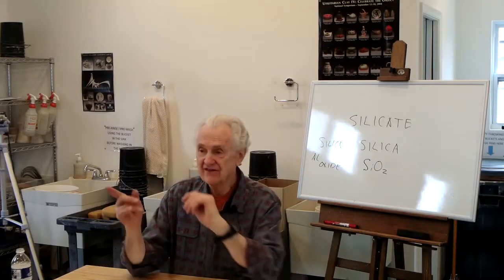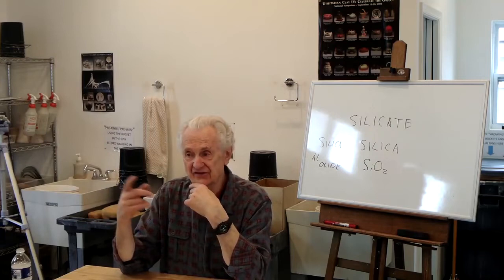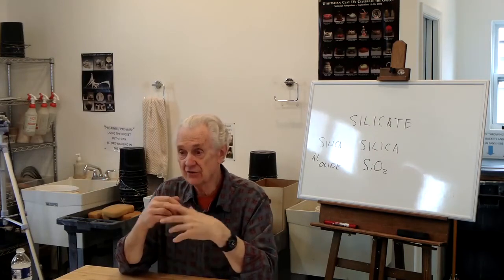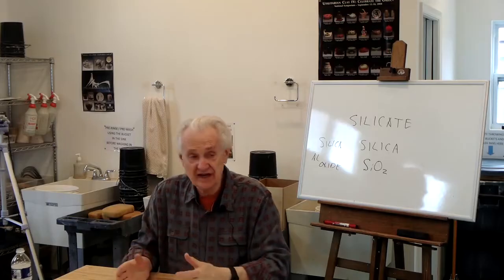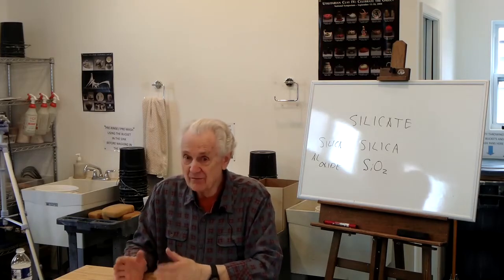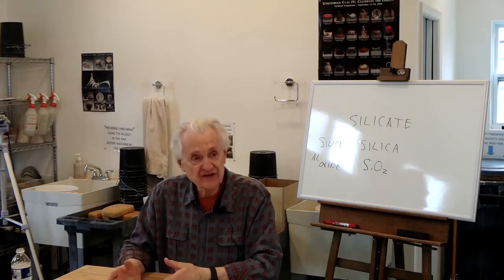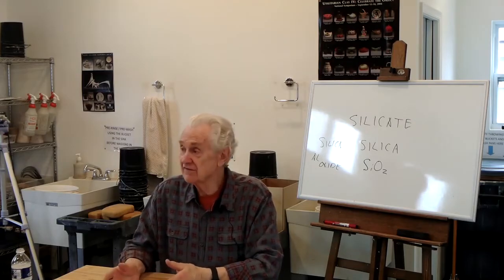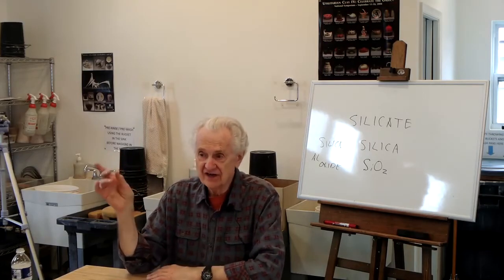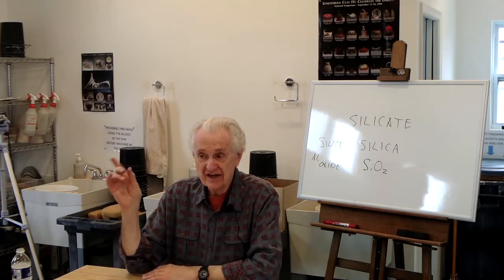And that's the same thing for all of the common glasses that we use: window glass, drinking glasses, containers. Those are all silica glass. They have slightly different properties from a glaze, but they're not that much different. They're all basically silica plus some other stuff. For instance, window glass is basically sodium oxide and silica and some calcium oxide, and that's it.